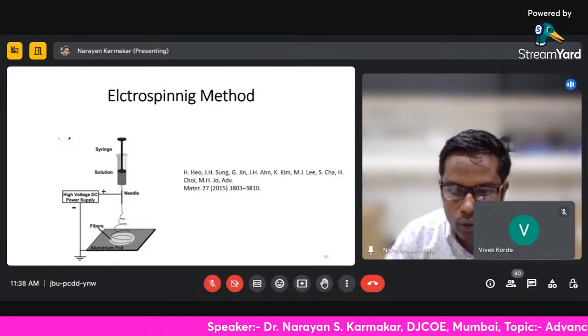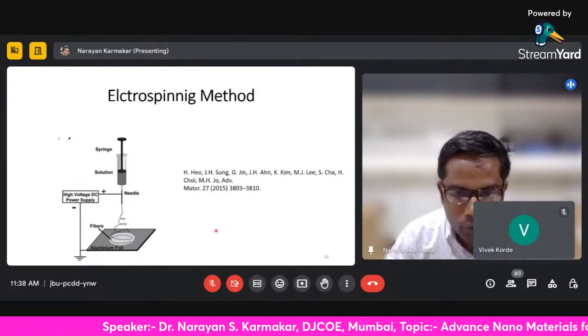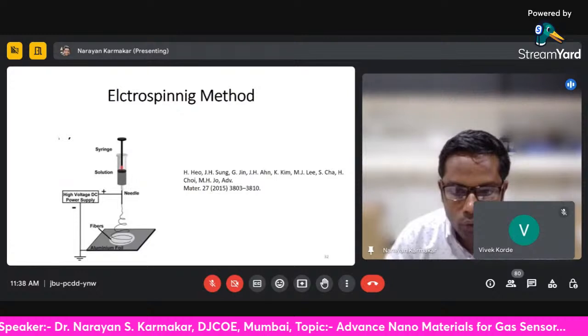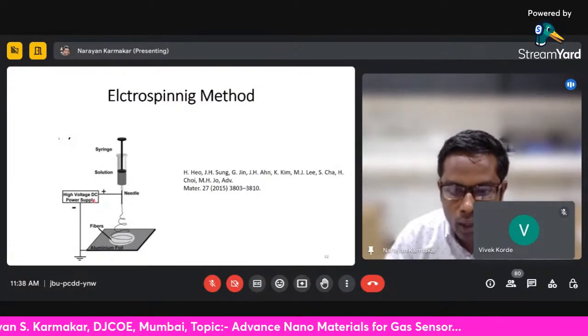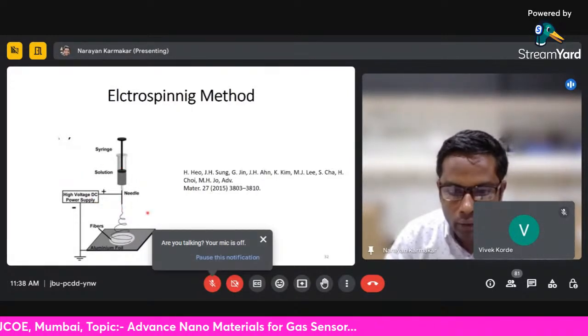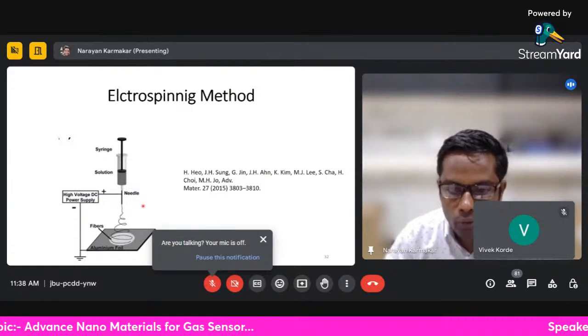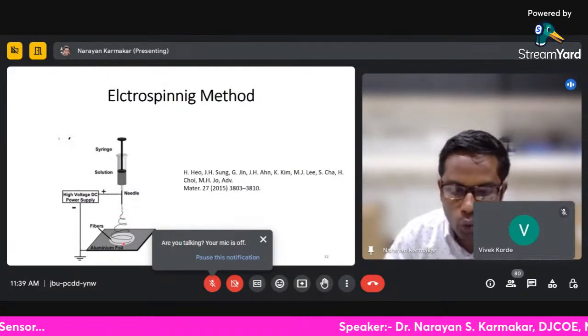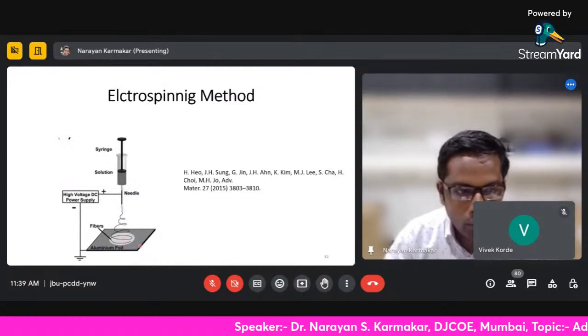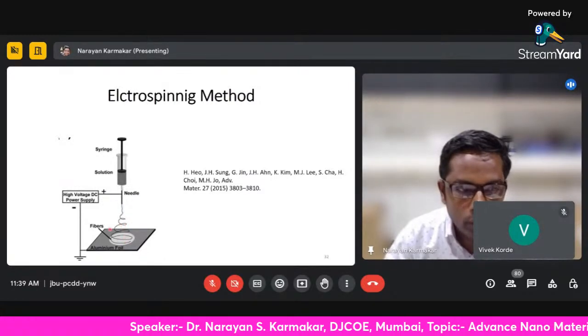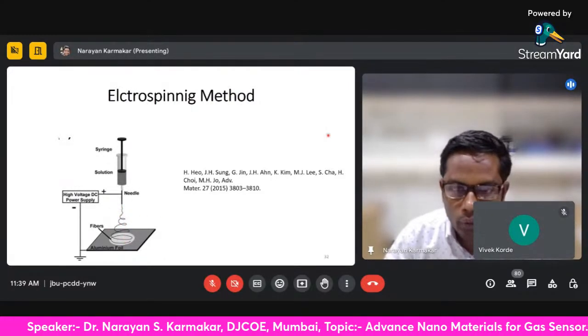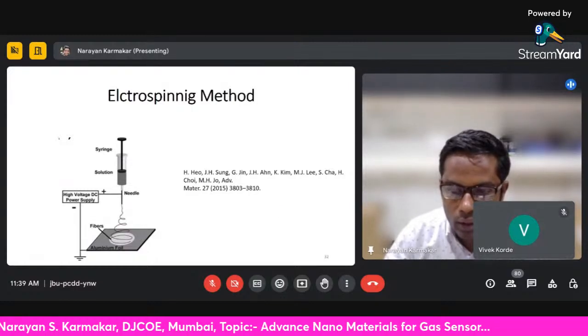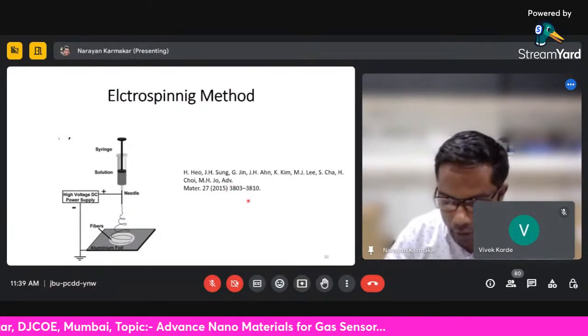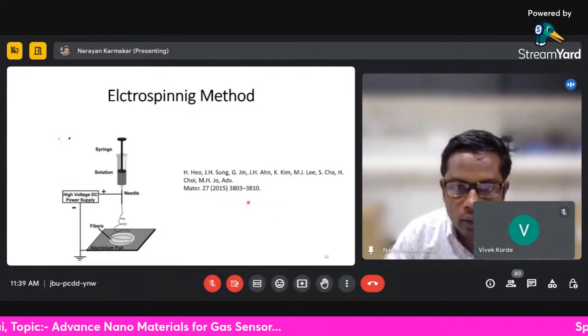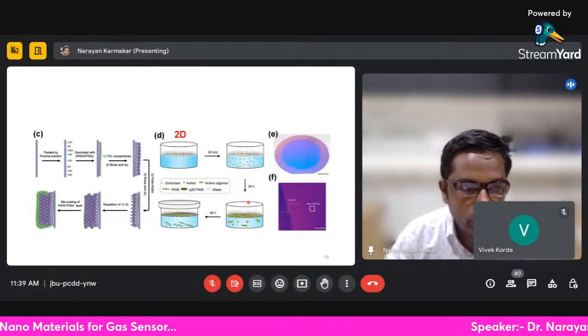And in this process, what you do is this: a polymer solution is first forced out of this orifice to form small droplets. And when you apply a very high electric field, because of this high electric field, a charged solution jet is extruded from this cone. And because of that, we have a very thin fiber coming out from this needle. So these are some of the ways where we can synthesize nanoparticles or nanowires.